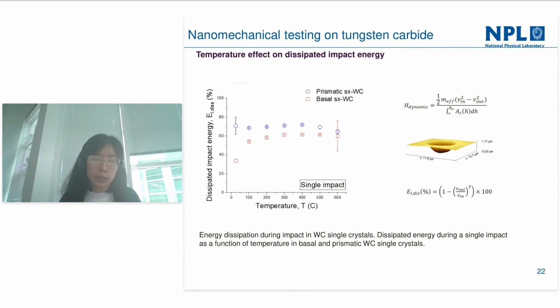With the recorded displacement data over time, we were able to calculate the velocity, which was used to calculate the dynamic hardness according to the energy method here, without including the work of the acceleration force, because the depth recorded during the first bounce is not purely a plastic response. The volume of the indent was measured with built-in 3D scanning, with a sharp indent at a very low load of about 1 micronewton. The crater of the indent is shown in the yellow images on the right.